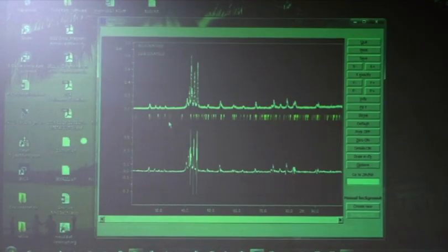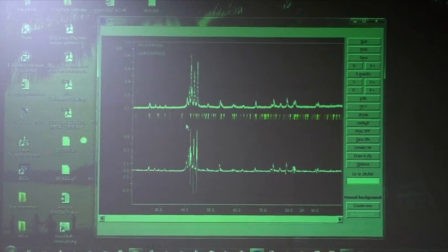So our R factor is quite large for the moment. Open the listing, no. And we open the profile viewer, and we get things like this. So we have green lines and we have white lines. The whites are the main peaks and the greens are the modulated, the satellite peaks, sorry. Due to the satellite peaks. So okay, let's go back to our edit profile.